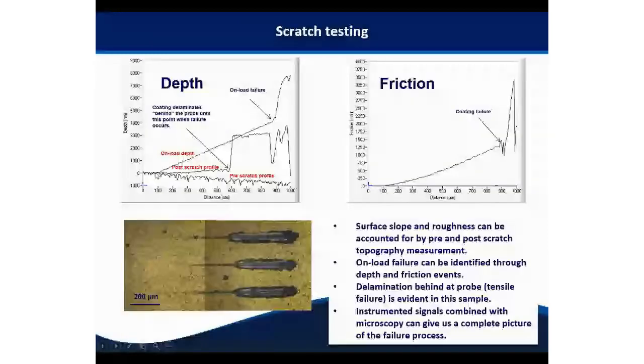So scratch and wear testing, typically what we do is we do a profile of the sample surface. So here's our surface roughness. So this is depth versus distance. Then we apply our scratch load. So we scan along, we return to the beginning, we apply our scratch load. At a certain point, the depth suddenly increases. Something's happened. We don't know what's happened at this point, but our instrument tells us something's happened. We then do another topography along the scratch path, and we see this big step here, which we saw no evidence of in our loaded pass. So what this is telling us straight away is there's some kind of tensile failure that's taking place in this coating substrate system. So that's an adhesive failure. And as we just saw, adhesion of coatings is very important.